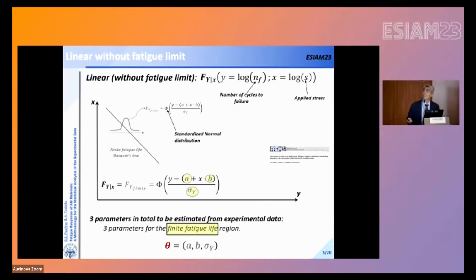And this linear variation is taken into account in a probabilistic model that has the mean value, as you can see here, that linearly depends on the logarithm of the applied stress, and a constant standard deviation. Here you can see that the probabilistic distribution that defines the probabilistic SN trend is a function. This phi is the normal distribution.